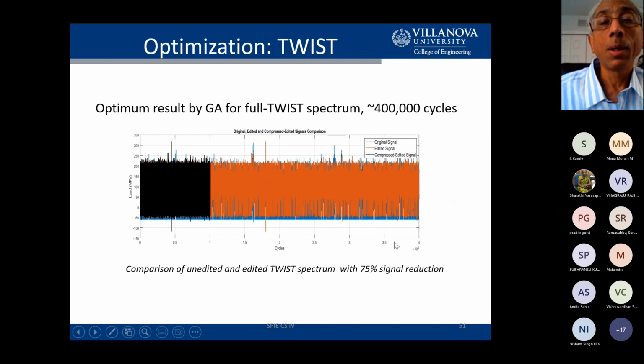The red region here, which starts all the way from the left all the way to the right, is the full spectrum. That's the original signal. And then the black portion here is your compressed edited signal. So we've achieved a significant amount of compression by eliminating, again, the high frequency parts that don't cause much damage. And we made sure that the damage between the full spectrum and the edited spectrum is not different by more than 5%. So that was our constraint.